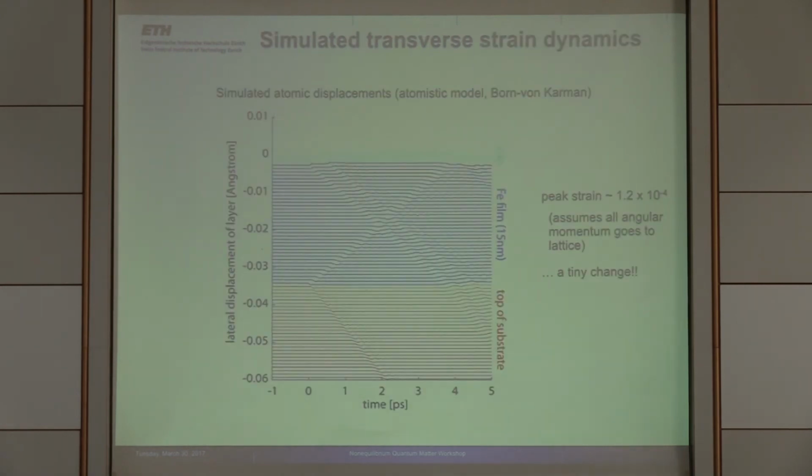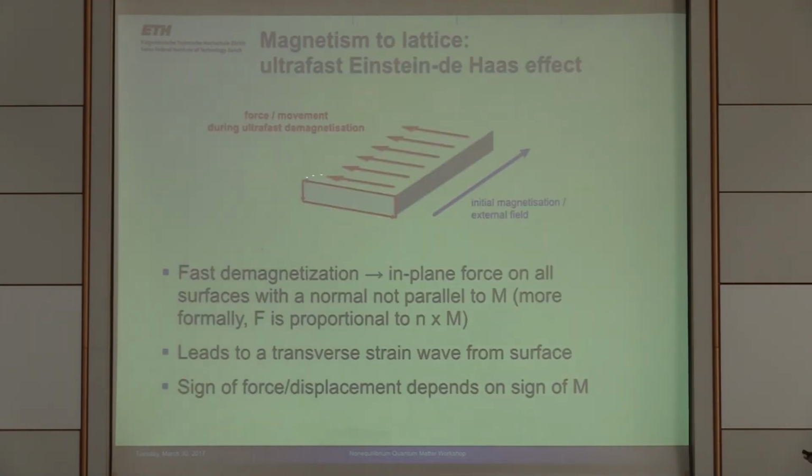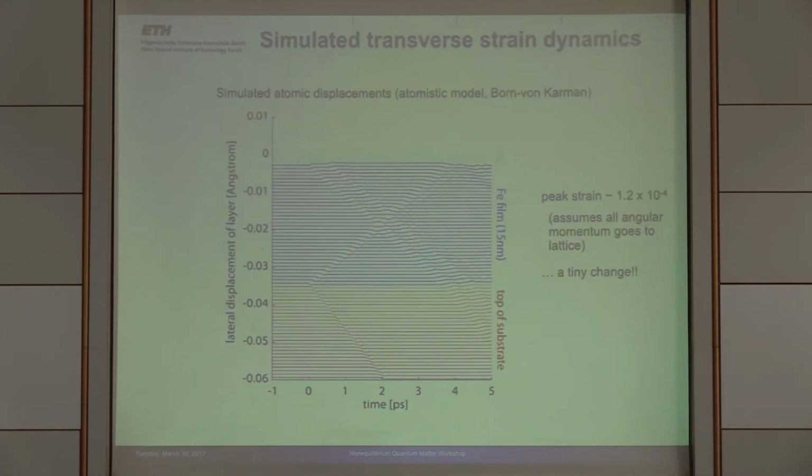All right. Okay. So getting to the time-resolved experiment. What we're doing is we end up not doing the experiment on a rod that we illuminate, because that's a really hard experiment. Instead, we're taking a section of the surface, which means we're looking at a film. And what we do in the experiment is a calculation based on the idea that angular momentum transfer occurs within 100 femtoseconds and follows this local phenomenon for a layer of iron that's demagnetized, with a capping layer that's non-magnetic and a substrate that's non-magnetic.